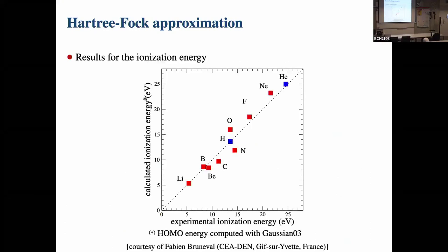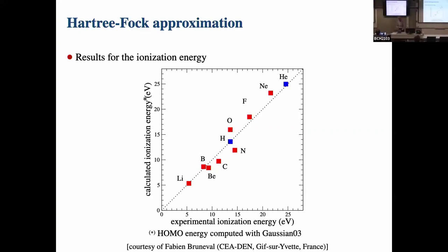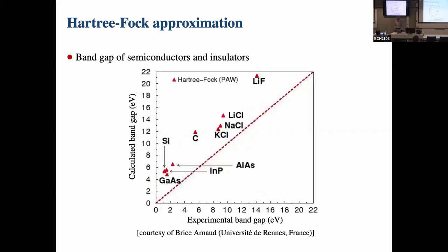Okay. So when you do that for molecules, it works rather well. This is some work that Fabien Bruneval has done, and he compared the two. When you look at the experimental ionization energy with respect to the calculated one, you see that the agreement is very reasonable. Now, that's for atoms and molecules. If you do the same for crystalline systems, so semiconductors and insulators, you see that Hartree-Fock clearly overestimates the band gap that is measured experimentally.